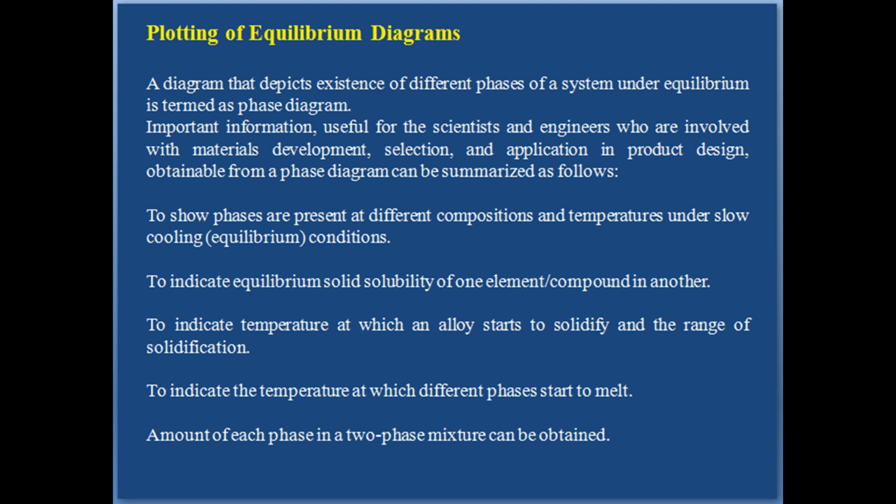A phase diagram is actually a collection of solubility limit curves. The phase fields in equilibrium diagrams depend on the particular system being depicted. The set of solubility curves that represents the locus of temperatures above which all compositions are liquid is called the liquidus, while the solidus represents a set of solubility curves that denotes the locus of temperatures below which all compositions are solid.